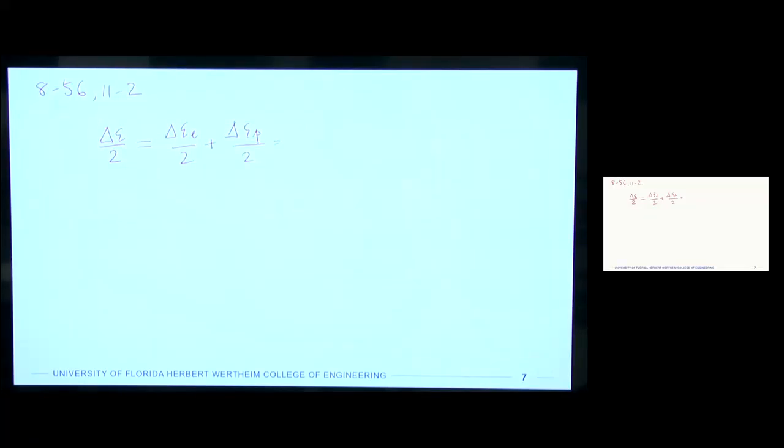All right, so we'll have in the elastic regime sigma prime F over the modulus, 2NF to the B, plus our strain fatigue coefficient, 2NF to the power C. So it's basically a summation on a log-log scale, which is a superposition of two power functions like that.